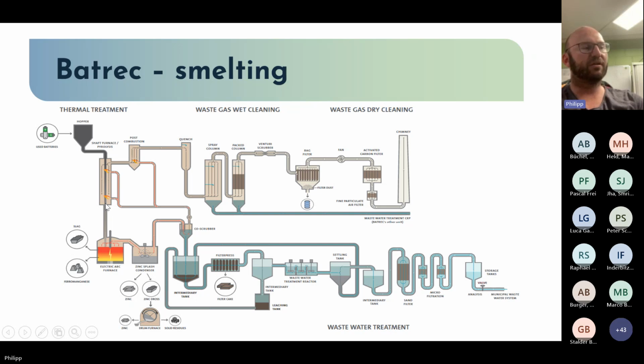The dry material we receive after the pyrolysis process is going to this electric arc furnace. There we have temperatures of around 1500 degrees. So we form the ferromanganese. It's settled down because of density. On top we have the slag where the reaction will happen. For example, the reduction of zinc oxide with carbon to metallic zinc. Then the metallic zinc will be vaporized, and we can condense this metallic zinc in the zinc splash condenser.